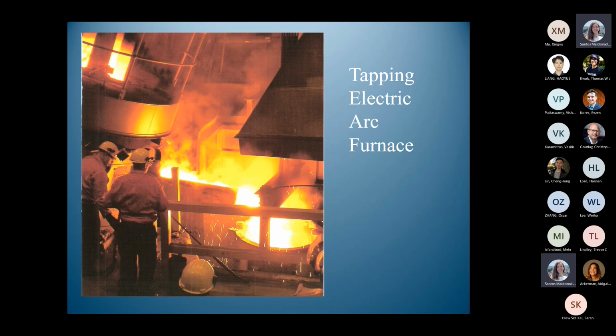Okay, the oxide oxide films are very different in density in steels. So they rise very quickly. The big oxide films will float out really quite reasonably quickly. So by the time the ladle's brought up out of the pit, carried over the foundry, comes down into the place where the castings are going to be made, and they open the stopper on the bottom, during that time, a lot of the defects will have floated to the top, and on top of the steel, there's a layer of slag now about 100 millimeters deep, which is all the oxide films which have floated out.